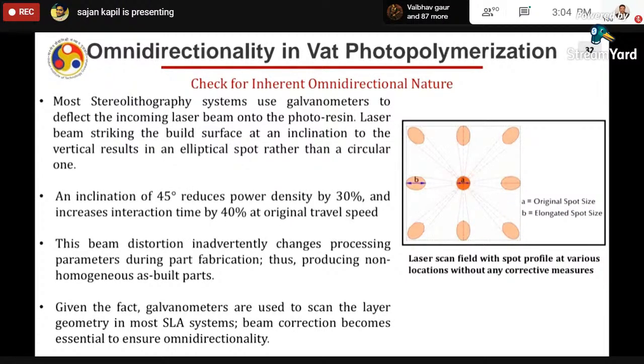An inclination of 45 degrees reduces power density by 30% and increases the interaction time by 40% at the original travel speed, and hence spoils everything. This beam distortion inherently changes processing parameters during the part fabrication, thus producing a non-homogeneous build part. So what you get here is a non-homogeneous part. Given the fact that galvanometers are used to scan the geometry in the SLA system, some beam correction has to be done to assure the omnidirectionality. Now this correction we are not going to do on the process parameter side. If you do that correction on the process parameter side, it will not be omnidirectional. You are going to do something with the machine tool system.